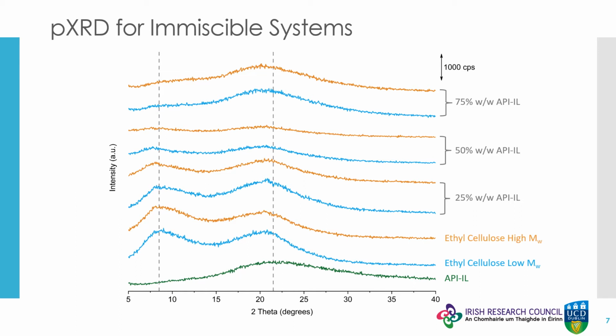Low molecular weight grades exhibit diffuse peak maxima at approximately 8.5 and 21.5 degrees 2 theta, while the maximum value for the API-IL can also be found at 21.5 degrees 2 theta. Dried products with higher ratios of API-IL to polymer show a gradual decrease in the intensity of the peak at 8.5 degrees 2 theta, while the peak at 21.5 degrees 2 theta remains unchanged. Similar composition dependence of the amorphous halos has previously been described in the literature as being indicative of phase separation.